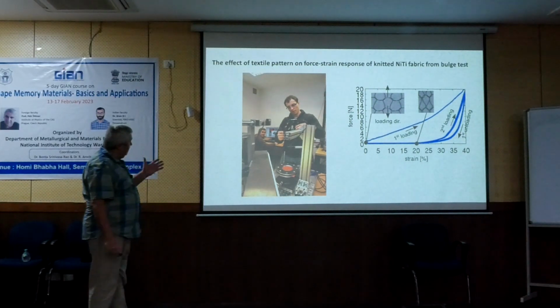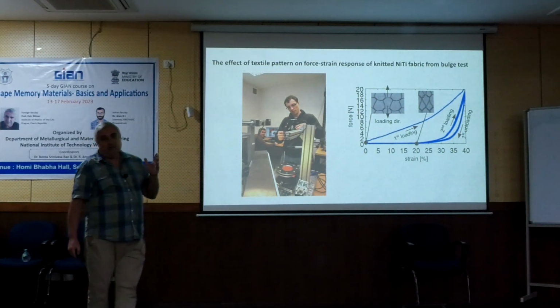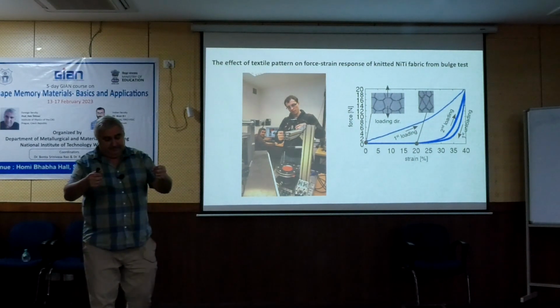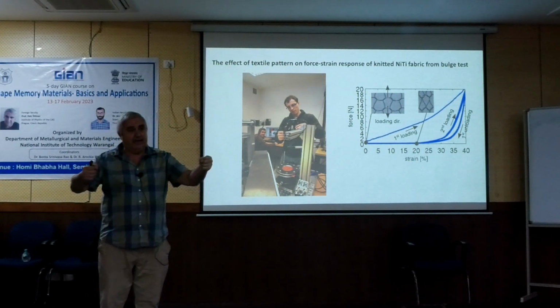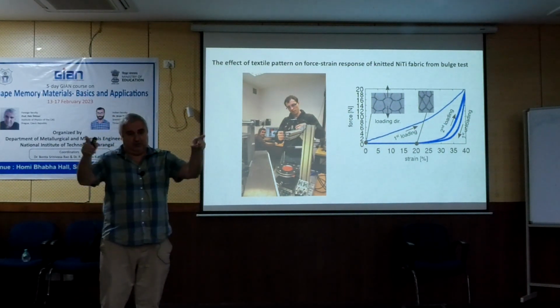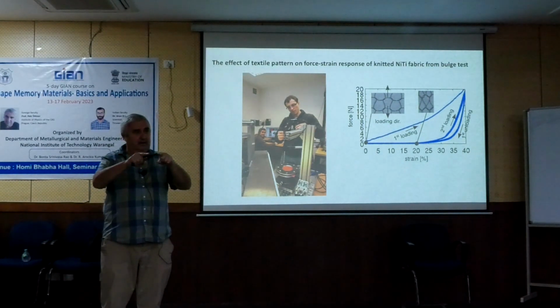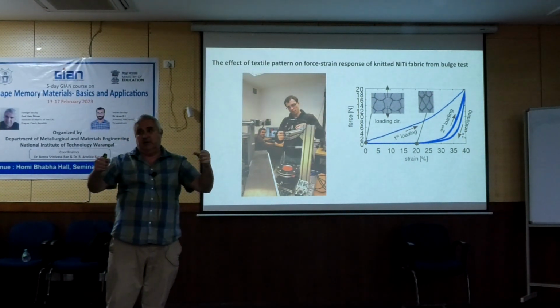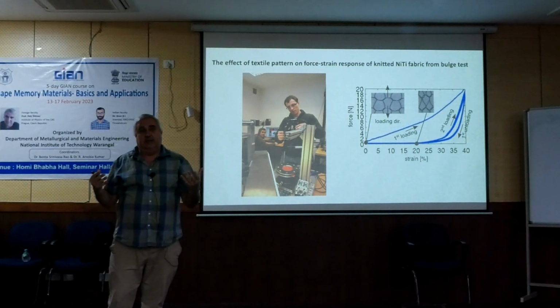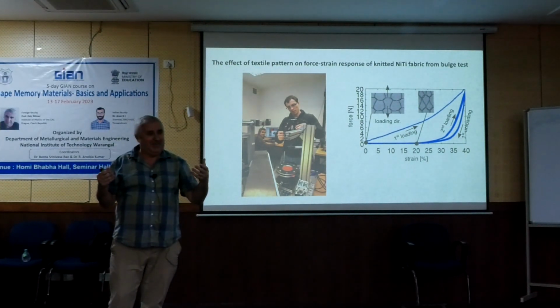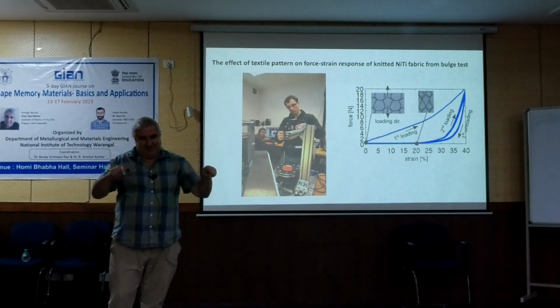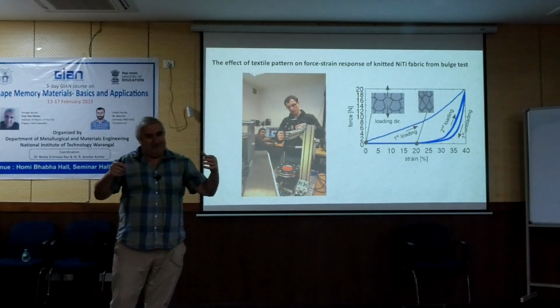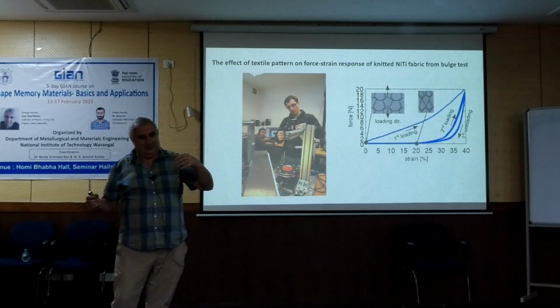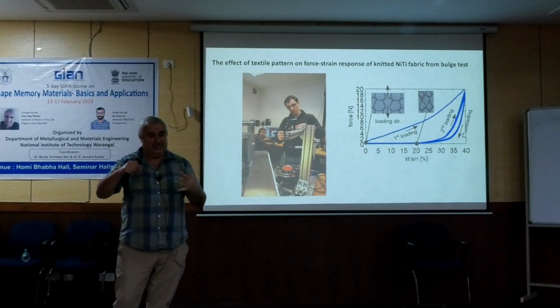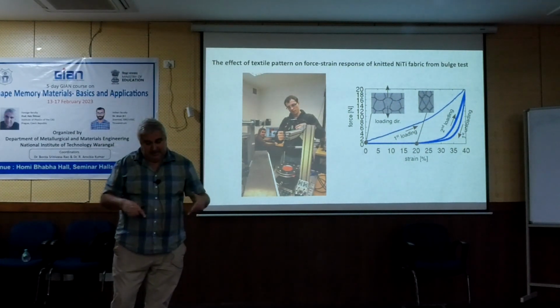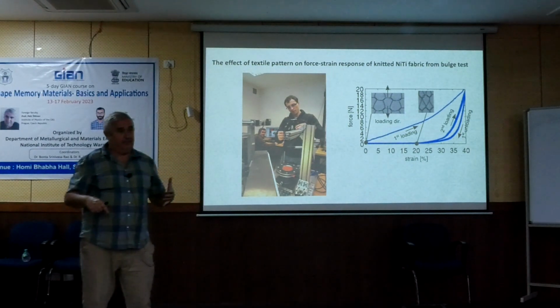Well, one of the very good tests was, if you have the textile loaded in one direction, it is kind of strange because it will create this type of profile. So you do the biaxial stretching. But if you do biaxial stretching, this is also strange because you will have some problems, more tangent here, more tangent here. So we had the biaxial rig, but we didn't like the biaxial rig.